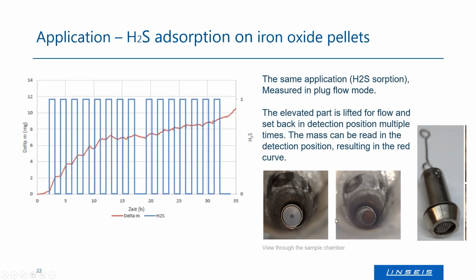Then you lift it, you bring it into weighing position, you determine the weight, then you lower it again, you switch on the gas again, there's some gas applied, you bring it up again, you measure the weight change. And doing this stepwise: put it there, float it with gas, lift it up, measure the weight, put it back to the bottom, float it with gas, and so on. These cycles can be done very fast, very precisely using the magnetic suspension balance. And this results in a graph like you can see on the left side.